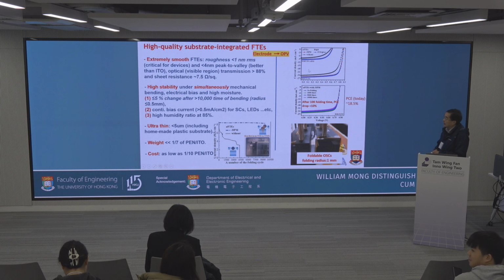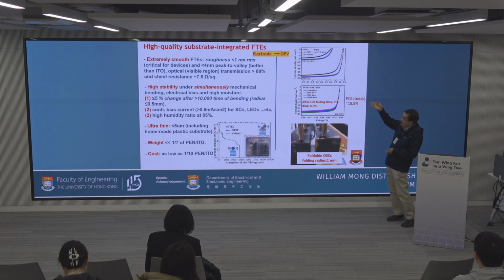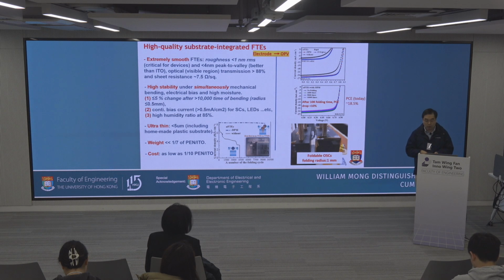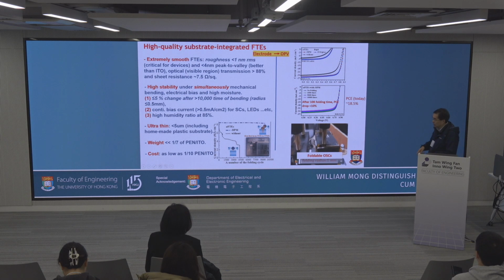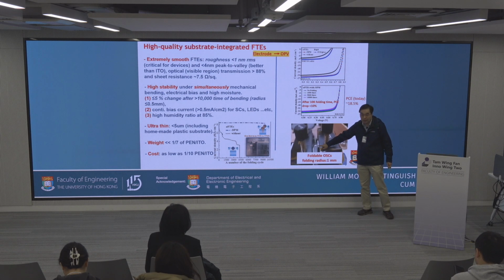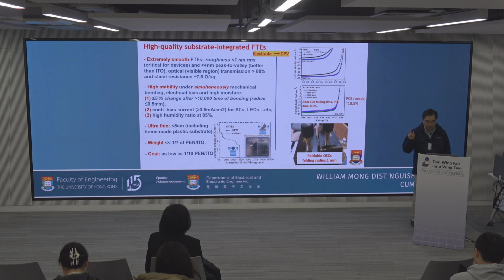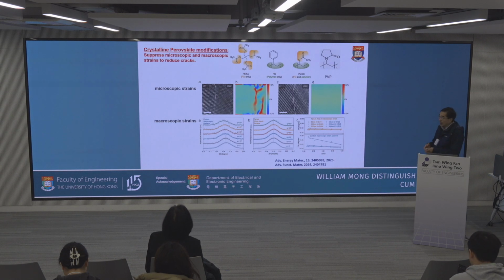We make it, and I'm not a chemist, so I borrow the material from another group. They are good at making organic acceptor and donor for active layer material. So we borrow all the organic material. We try to show that with our electrode, we can make the performance good. In OPV, we are now about 20%, which is reasonably good in the OPV field. And the bending test tells you that we are foldable, not just flexible, with bending radius less than 1 millimeter. So now we start with a good point.